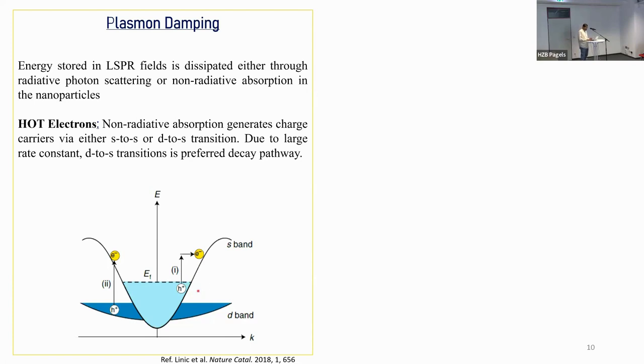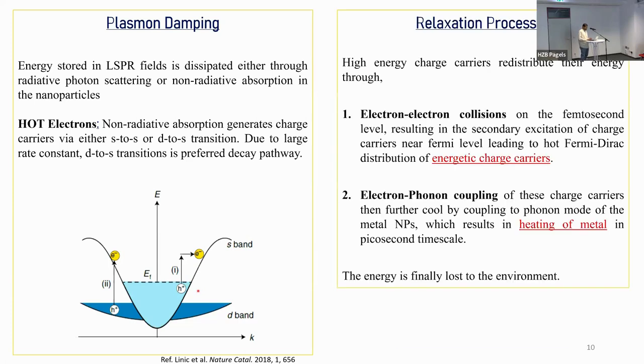However, there are other relaxation processes where, while these hot electrons undergo further relaxation, they undergo electron-electron collisions and you form another group of hot electrons, still above the Fermi level, which has a better lifetime, hundreds of femtoseconds. And those electrons, known as the Fermi-Dirac distribution of hot electrons, can be injected into the CO2. I'm just giving the example of CO2. It can be any reactant molecule.